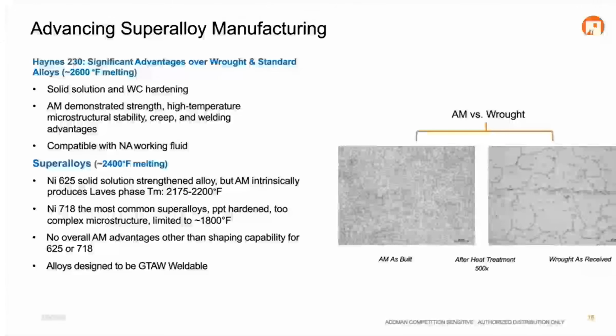Same thing for Inconel 625 — it's not precipitation strengthened, but solid solution strengthened. But it has some issues, especially around laves phase formation, and there's a lot of molybdenum in there that isn't necessarily as effective as a solid solution strengthener at higher temperatures.